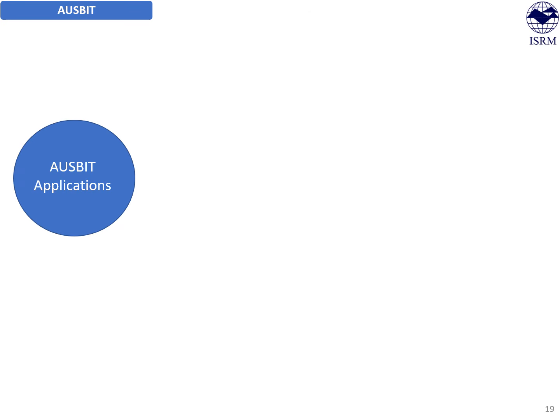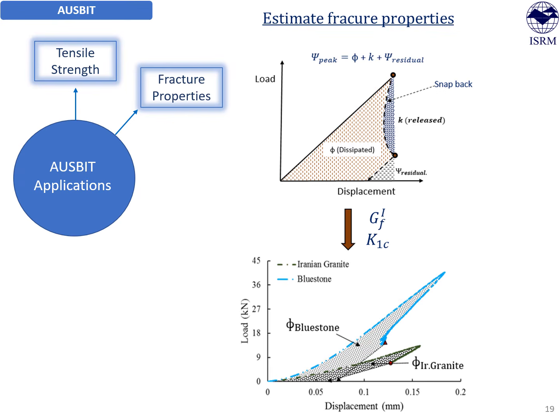But what are the other advantages? If we list all the benefits of AUSBIT applications, we can start with tensile strength estimation, which is, of course, already there. Apart from that, we can calculate the fracture properties of rock. In AUSBIT experimentation, we can capture the snapback response or true mechanical post-peak behavior of the disk specimen, which wasn't possible in the conventional approach. Now, because of this snapback response, we can calculate the excess strain energy and the strain energy required to create the vertical diametrical crack.